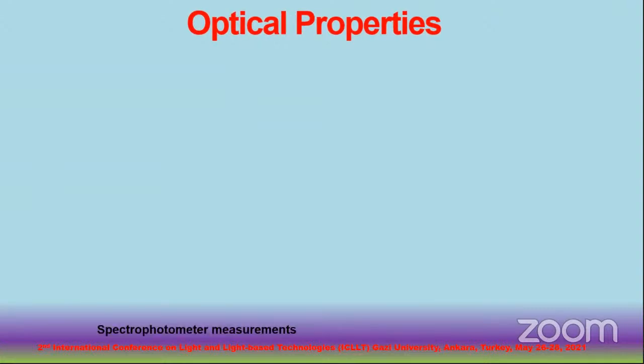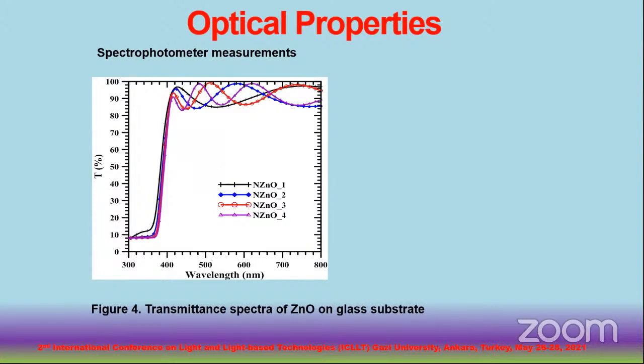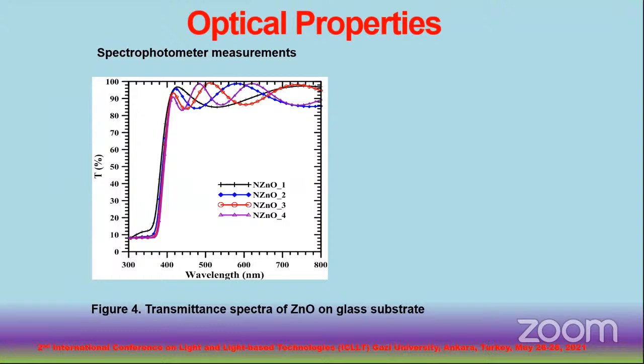Optical properties. Spectrophotometer measurements. In order to determine the optical properties of nitrogen-doped zinc oxide films grown by changing the thickness, the transmittance, T%, of the films was measured in the wavelength range of 300 to 800 nanometers at room temperature. In order to ensure that the optical transmittance values of the films are independent from the substrate absorption, transmittance measurements were done referring to the glass substrate.